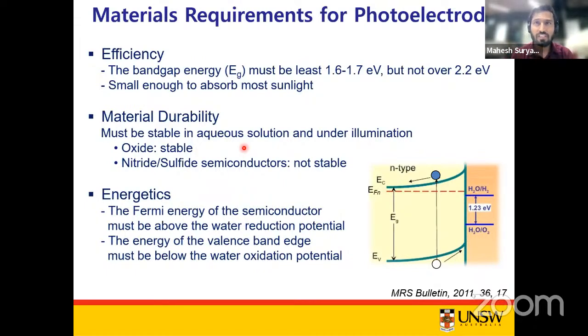Additionally, because the number of incident photons received per unit area in these semiconductors under standard conditions is usually fixed, to match these kinetics the material should be catalytically active for either the oxidation or the reduction reaction, or for both, and can be effective in transferring and transporting these photogenerated charge carriers among themselves. In addition, the candidates need to be resistant. That means it should be highly durable in the water electrolyzer, and should survive long reaction in water under intense illumination.